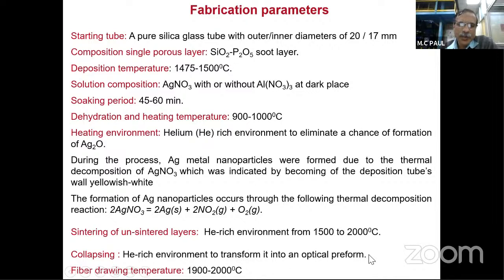Then we make a preform. The preform is a solid rod of around 10 millimeter diameter. Within the 10 millimeter diameter, the pore diameter is around 0.1 millimeter, where silver nanoparticle is doped. From this preform, we draw a fiber. This is the MCVD first porous layer.